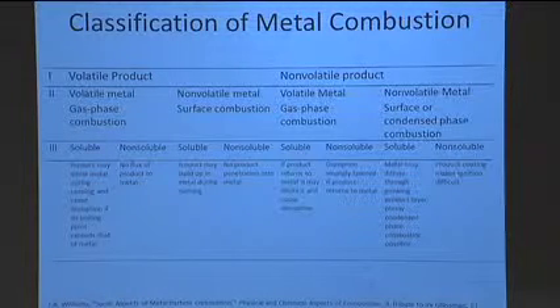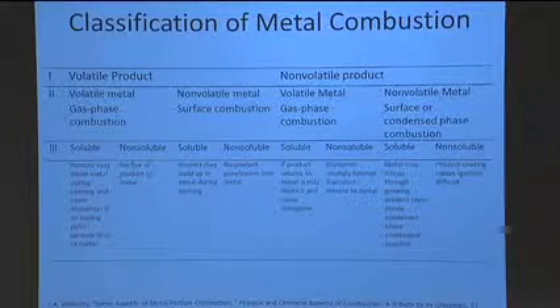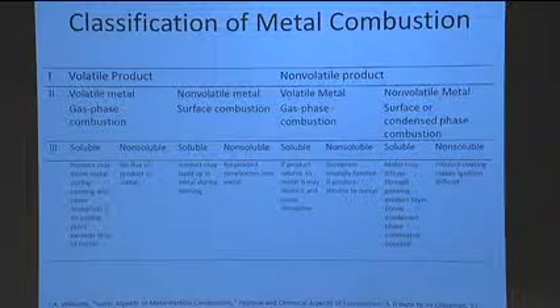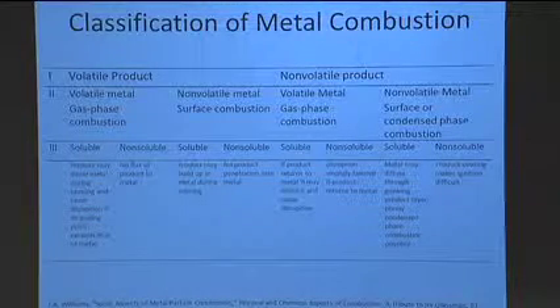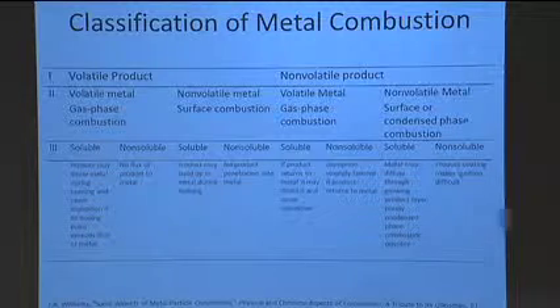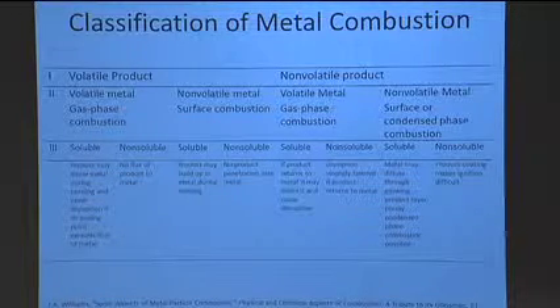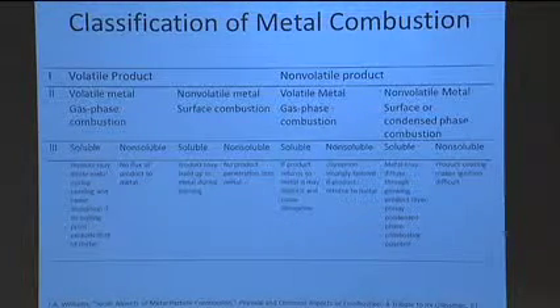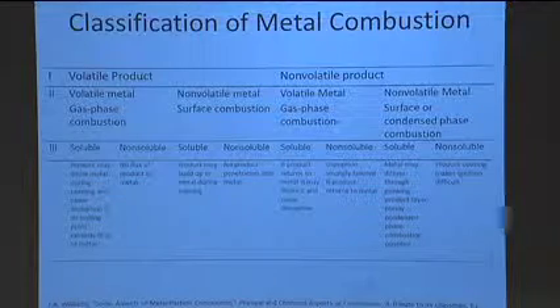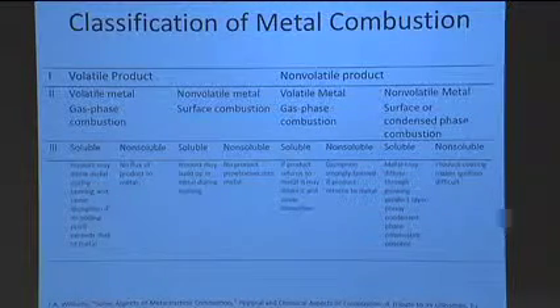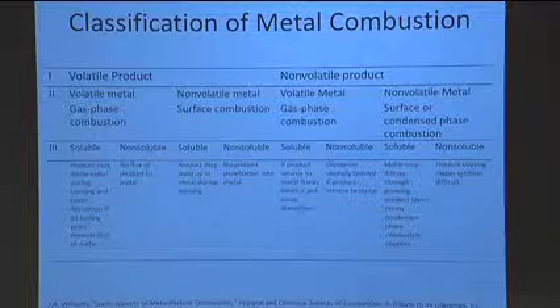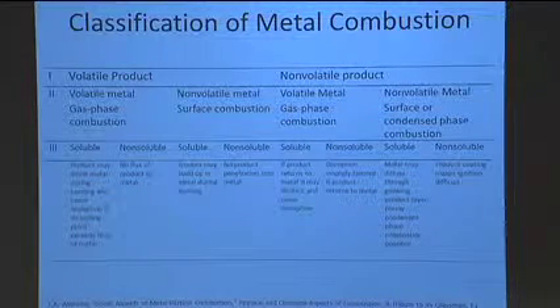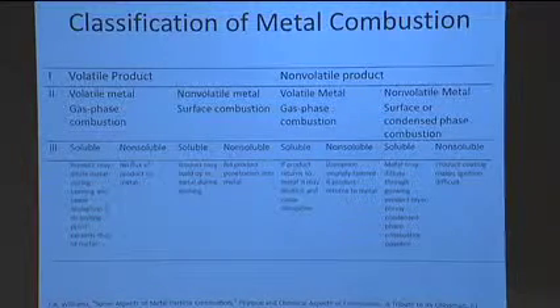And if I come down to this third discrimination, the importance of this is really, in some cases, how the material might burn itself as it's burning. And in particular, if you see that the product is highly soluble in the original fuel, you can actually start to get some interactions between, say, absorbed oxygen and phase changes where you actually get disruptions. And so I could have a disruptive burning process.